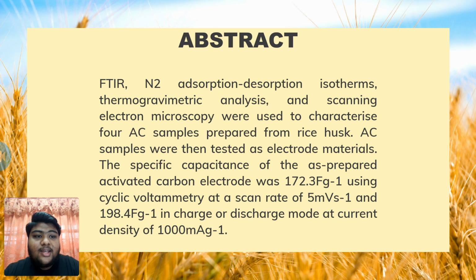The specific capacitance of the as-prepared activated carbon electrode was 172.3 F/g by using cyclic voltammetry at a scan rate of 5 mV/s and also 198.4 F/g in charge/discharge mode at a current density of 1000 mA/g.